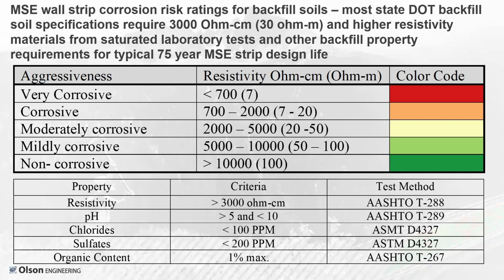The chlorides, they also found problems with chlorides and sulfates. The organics were fine, but these are the criteria that the Department of Transportation or MSE wall designers will look at to say this is what the properties of the backfill soil should be. So what I'm indicating is that laboratory testing, in addition to the resistivity work we did, indicated there were some areas that were more corrosive to very corrosive.